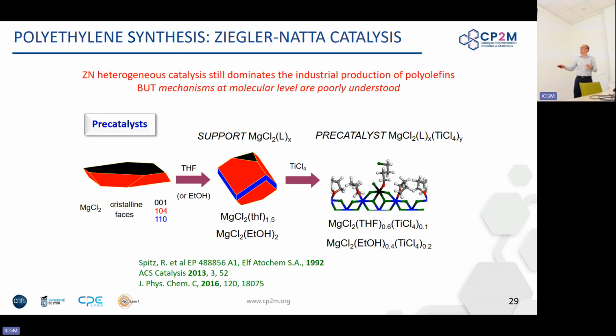So you take a Lewis base, and you will tune the number of magnesium dichloride and the way they interact with each other, depending on the choice of the Lewis base. Okay, so you will have layers of magnesium dichloride with some Lewis base that interact with the barely Lewis acidic magnesium dichloride. And then you treat that with TiCl4, okay? And you will get TiCl4 that is organized on the surface. And if you get lucky, you will have something that will turn into an active site upon alkylation and reduction.